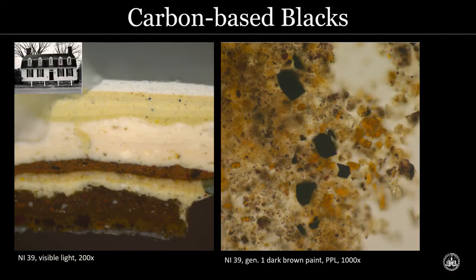So here we have a really excellent example of carbon-based blacks used in house paint. This is a sample taken from the interior of the Robert Nicholson house, which dates to the mid-18th century. One of the first layers is actually, again, not a red-brown, but a thin gray primer followed by a dark brown paint. And there were multiple layers of dark brown paint used inside the house in this period. And we have these enormous opaque black pigment particles in the cross section.